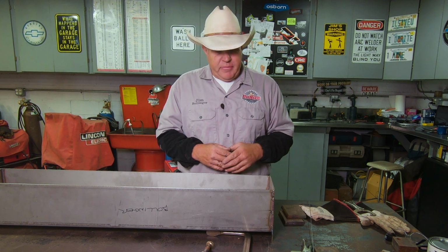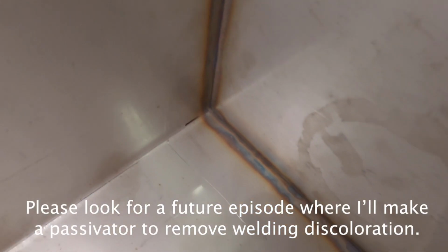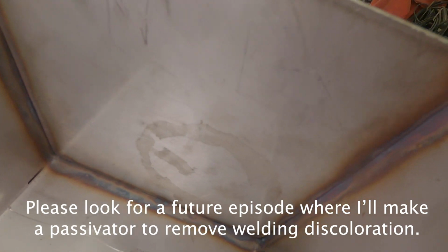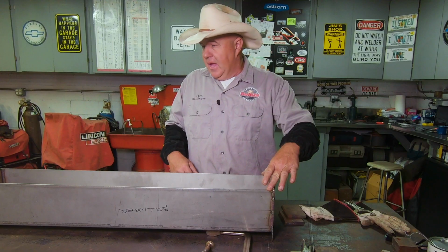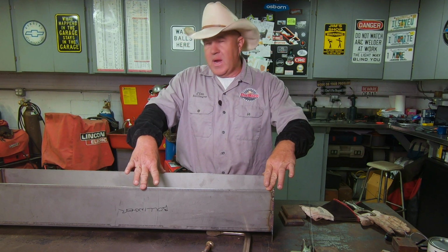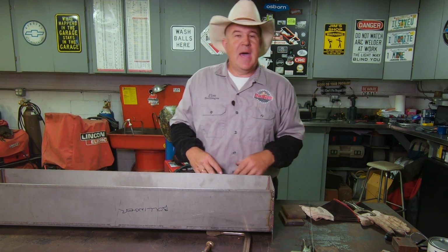There's a little bit of sugaring on one side there, and it's not real bad. Honestly, there's only one little spot right there. And I wanted to give you that comparison. I just went ahead and finished half of the weld without the copper bar on it, slapped the copper bar on the other side and welded it. There's a big difference. Inside here came out outstanding. Other than a little bit of discoloration from the heat, there is absolutely no sugaring of any kind, no distortion. Everything's great. It's a little tiny bit out of square here, just a little bit, not bad.